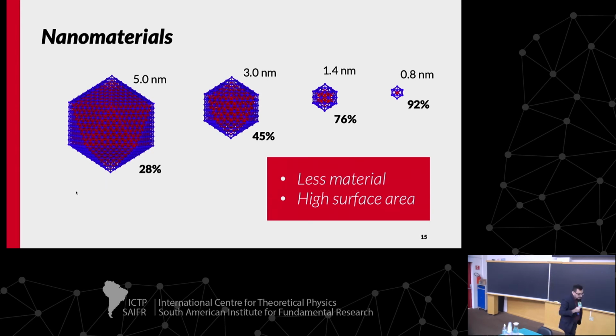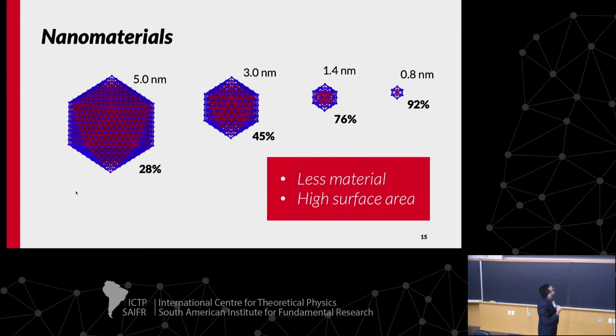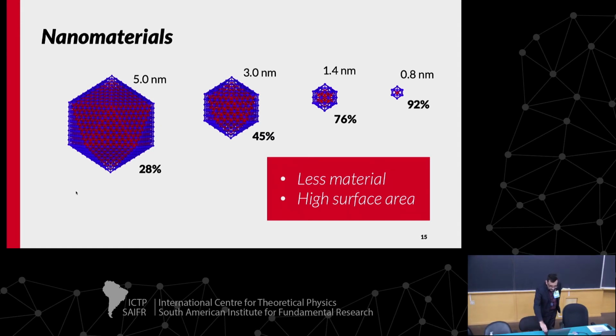To do this catalysis, we need to think about the surface area of the catalyst, so it is very common to use nanoparticles and reduce their size. When we reduce the size, the number of atoms exposed on the surface increases. For example, for a 5 nanometer icosahedral nanoparticle, 28% of atoms are on the surface. But for a 1.4 nanometer nanoparticle, 76% of the atoms are on the surface. This is important because catalysis is a surface effect, so we need a high surface area. Also, we can divide by the mass or quantity of platinum or iridium used, and with nanoparticles we can increase the catalysis per mass.